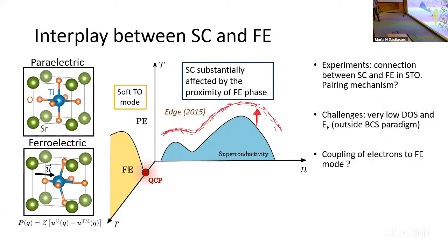So there have been a lot of experiments showing that if you move this axis, just for the sake of clarity, I have separated them well, but if you move this axis, you basically start doping. This is the charge of the electrons. It's happening electrons here and here and here. The closer you are, or the proximity to this phase, really affects Tc a lot. You get an increase in Tc of a factor of 2, 3, and so on. And so the experiments are suggesting that this phase is affecting it.